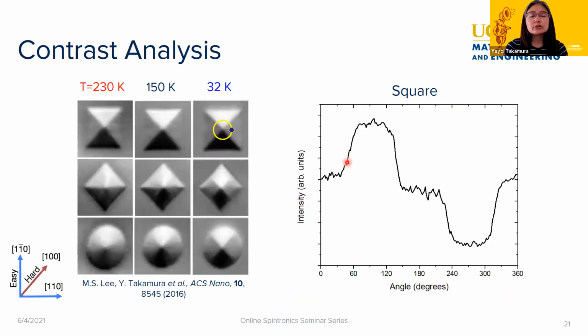So we thought, okay, those are really nice images. Can we be more quantitative? Can we understand how the magnetocrystalline anisotropy changes as a function of temperature? So we wanted to do some more analysis of these domains. I've actually switched the order here, so now high temperatures are on the left, low temperatures on the right. We went back and forth with different ways of analyzing this, but what we decided is to take a profile in terms of a circle in the center of the nanomagnet. So here for the square one at low temperature,